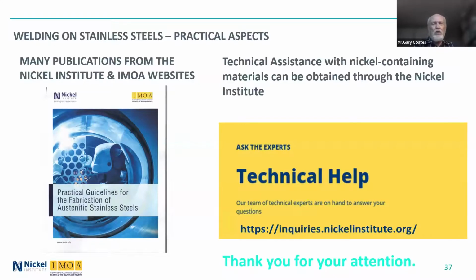So typically, most oil and gas people, where they know that this is a problem, will specify what we call a stabilization anneal, which causes all the carbon to be tied up with either the titanium or the niobium. Different oil and gas companies have slightly different temperatures that they think are optimum. But it is common to do that. And sometimes, in my own experience, you have to remind the fabricator that this is required. They will often have a stabilization anneal on the plate material in the first place. Do they want it on the weld? Ideally, you do want it on the weld.